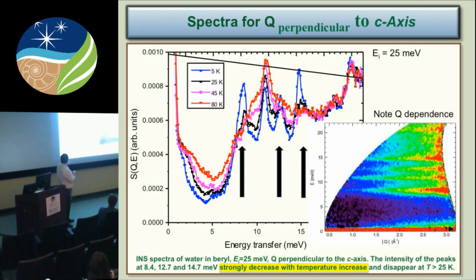What I wanted to show you, though, was to get into some more detail. Again, here's the shark fin diagram for this on the right. You can see a number of absorbances here. Again, not much of a slope to anything here, but there is a significant Q dependence to the intensity. We'll get back to that in a minute. Look at this peak and this one here. What you're looking at is the temperature dependence of these peaks within the material. Now, typically, a vibrational peak in a spectrum like this would be expected to get more intense as temperature increases. That's simply because as temperature increases, you're making it easier to populate that higher energy level, and so you're getting more and more transitions between the two.